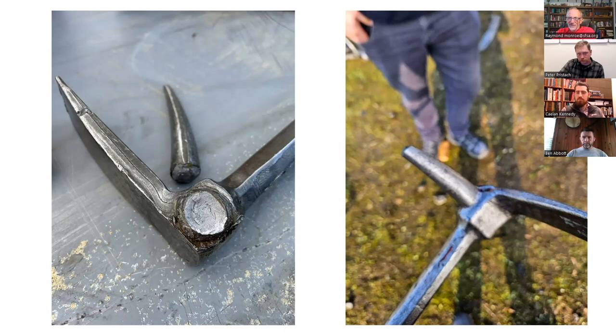Do they start out with a bigger bar and forge the bar part? The one on the left of your screen is a welded pick — I can see that weld all the way around there. That is a pretty popular break. Like, that outnumbered anything else — picks broken off of a Leatherhead. I've done it to two of them in the same morning, new out of the box. I know the guys that designed it; it does tend to break right there a lot. They fold the adze up and then weld on the pick in that case.